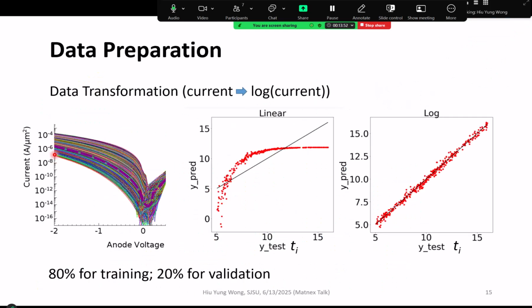So here we just show that if you have the right data, it turns out that you don't need a very fancy machine learning tool, right? Just a simple linear regression can do very well. It can predict the thickness of the intrinsic region well, right? Now, I have not told you that from device physics, the leakage here depends strongly on the intrinsic region thickness. And that's why it did very well when we trained it with those data. But it cannot predict the thickness of the other regions too well, right?